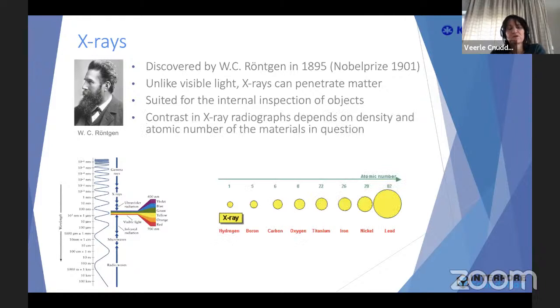What you measure with X-rays, or what you see in X-ray radiographs, which you are probably familiar with when your arm is broken and an X-ray radiograph is taken, depends on the density and the average atomic number of your materials in question. So if there is a difference, then you will have contrast in your radiographs, depending on the difference in composition of your materials.